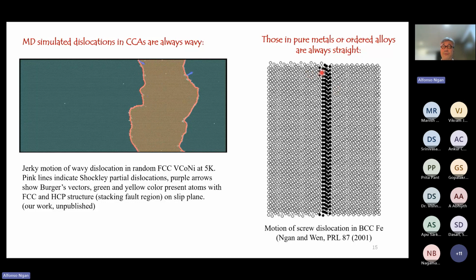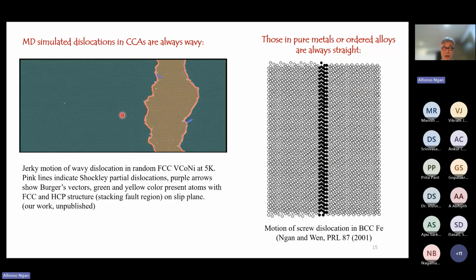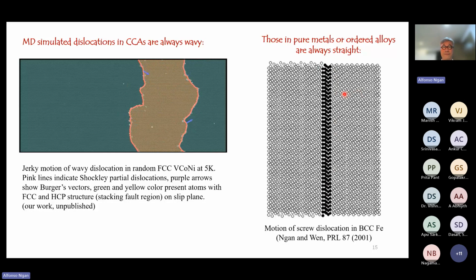While if you look at a pure metal, so this is just iron, again at a low temperature, also 5K or so, it moves via generation of a kink pair and propagation of kink pair. So most of the time, the dislocation is straight. The only fluctuation would be a kink, which is one atomic step in height, and then propagation of that. So this is a big difference between dislocation behavior in a CCA and in a pure metal or dilute alloy.